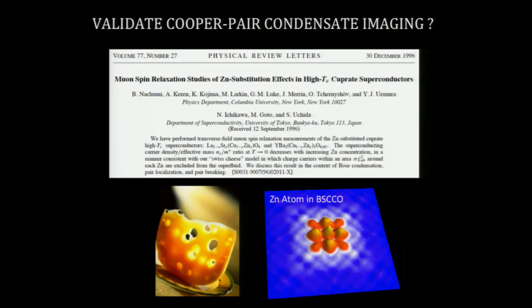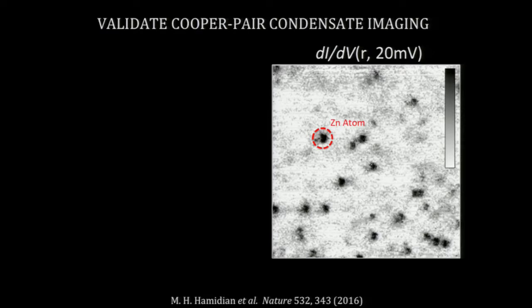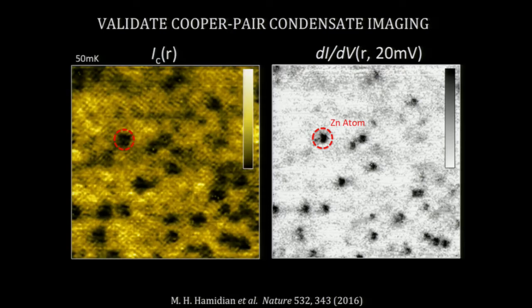It was shown a long time ago that if you put a zinc atom into the cuprates, very locally it punches a hole in the superfluid. It suppresses the superfluid density and creates sort of this Swiss cheese model of the superfluid. So now we go back into our single tunneling mode, and we can image where the zinc atoms are. So high is black here. So intense peaks are the zinc atoms. And then we, in the same field of view, create that image. And you see for every place there is a zinc atom, there is a suppression of the I_C map. So this was our way to validate that this I_C measurement is really a measurement of the superfluid density.